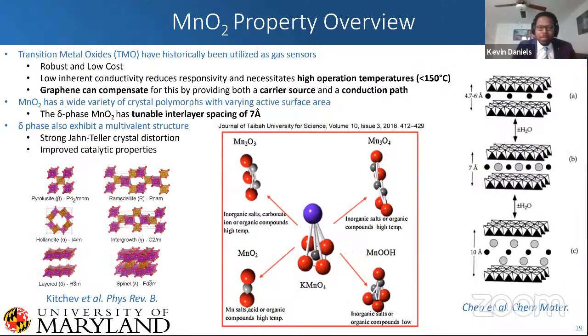Now, something that I didn't mention about graphene is if you heat up graphene with oxygen, your graphene will actually go away. It'll form carbon monoxide and carbon dioxide as it goes out the chamber. And so we were thinking, what is a way we can synthesize this material? And so one way is through electrochemistry.